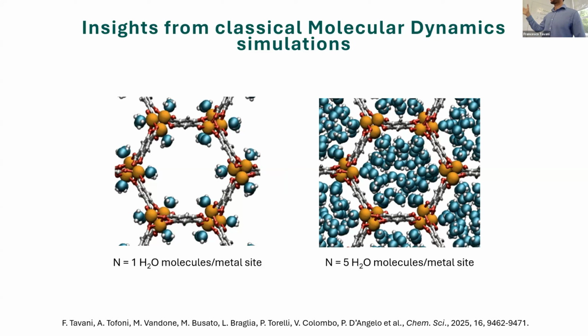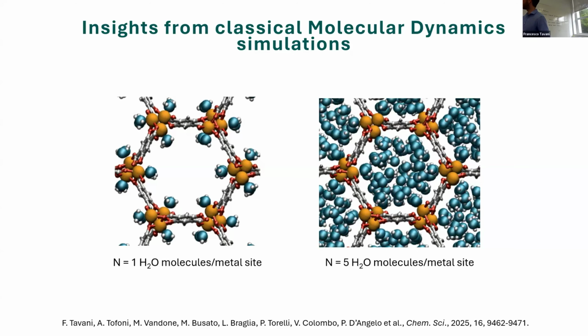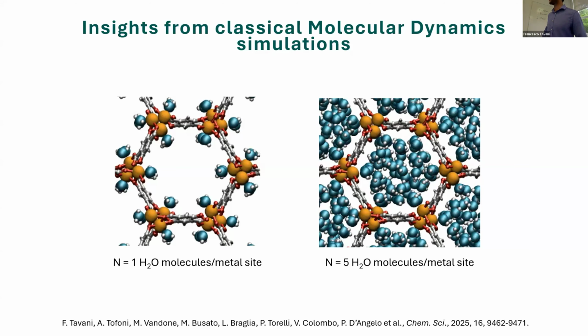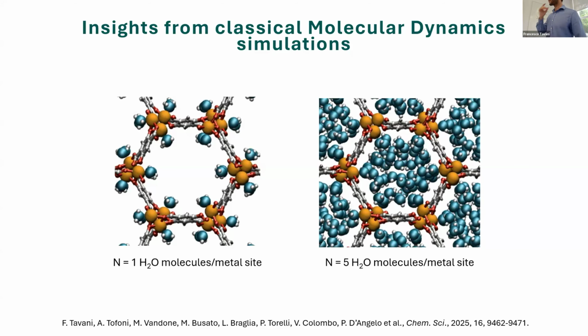These are simulations performed using a force field that was developed by previous groups. So if we consider a loading of one water molecule per metal site, actually these water molecules, and there has been a lot of work on this, are tightly bound to the metals. And if you remove them, you basically destroy the framework. So they're not bulk-like. If you increase the water molecule loading up to a maximum amount of 5 water molecules per metal site, of course, we have the pore fully populated by water.